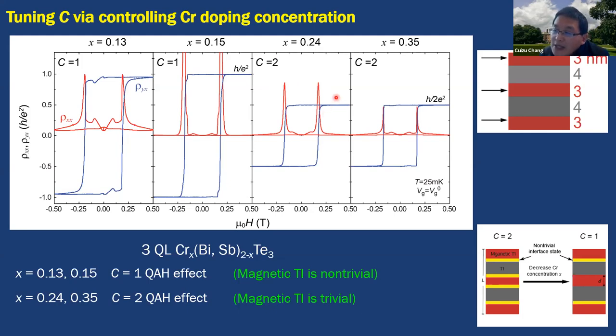The reason is that, as I just told you, with the lower doping level, this layer is still topological. This is the topological undoped TI layer, and the three layers share the same topology. So there are only the top surface state and the bottom surface state, and each surface contributes e squared over 2h. So the total is e squared over h. This is just the C equals 1 quantum anomalous Hall effect.